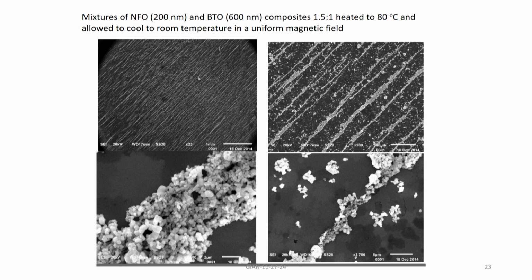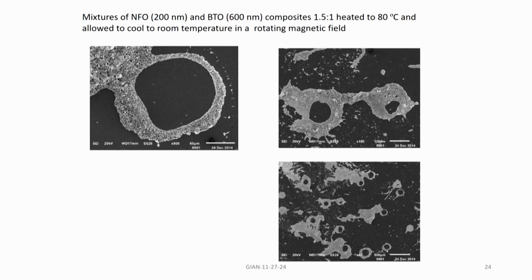And these are at different concentrations. Initially they were heated up to 80 degrees, so they dehybridize. Then you apply a magnetic field and cool them down, and they hybridize and line up along the field direction. Especially this one looks nice. We also assembled this in a rotating magnetic field, with the magnetic stirrer just rotating. You spread these particles and you see nice rings of these coarser particles under a rotating magnetic field.